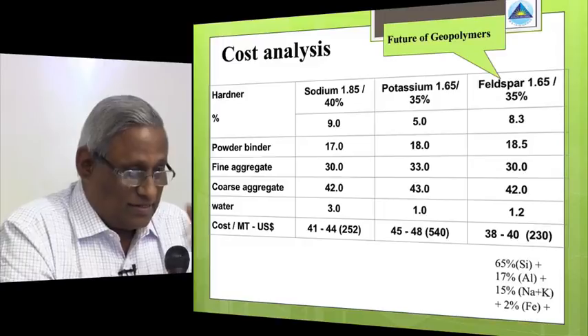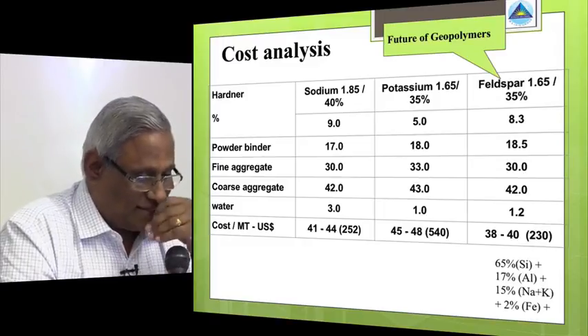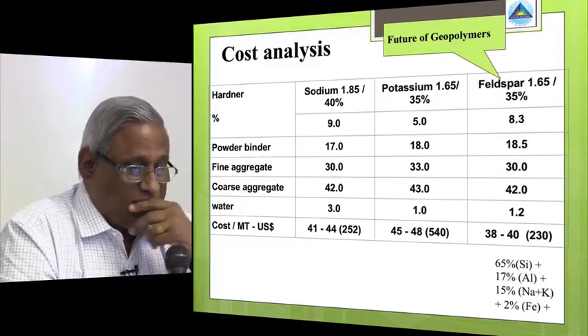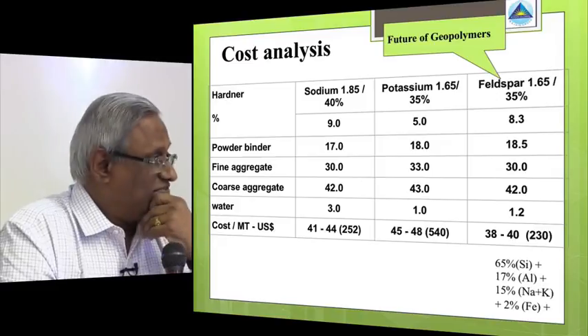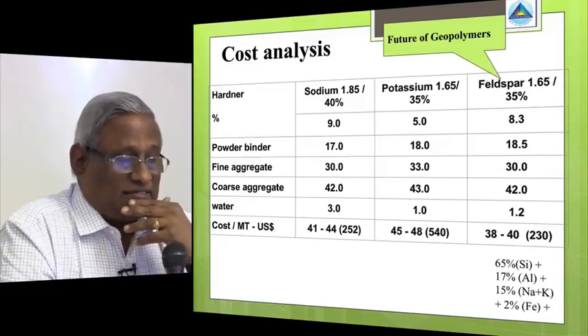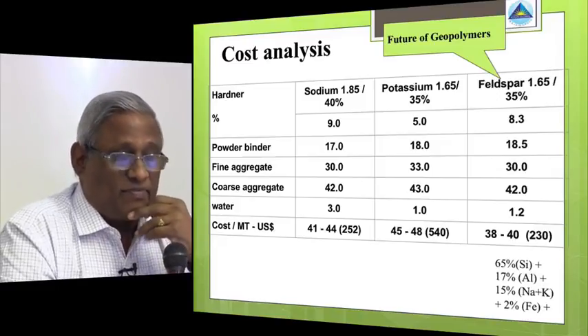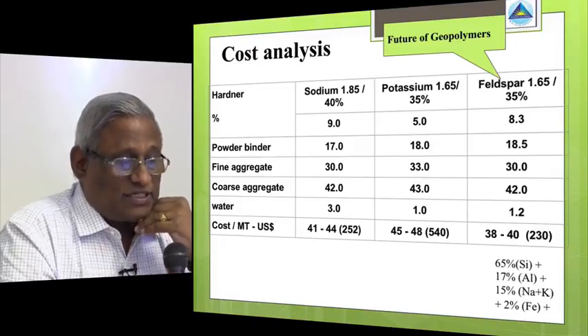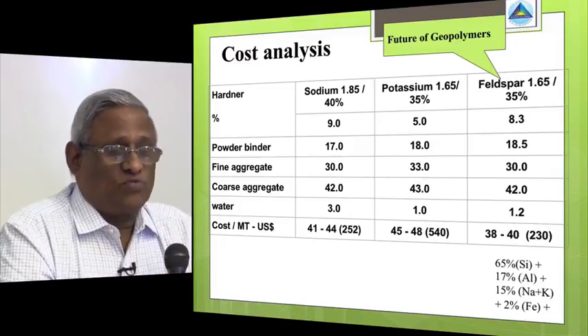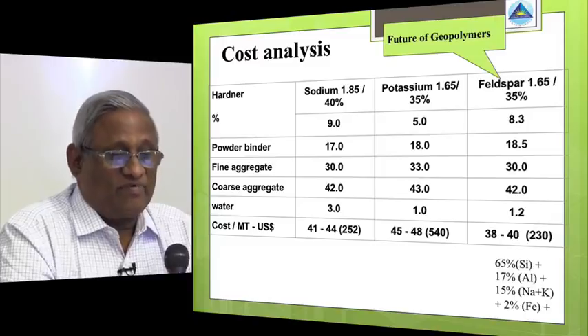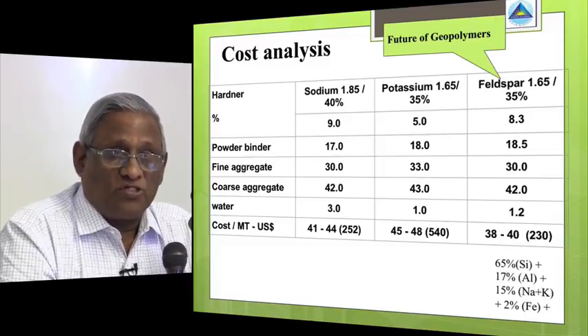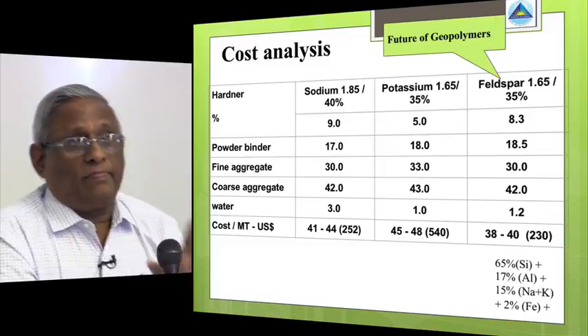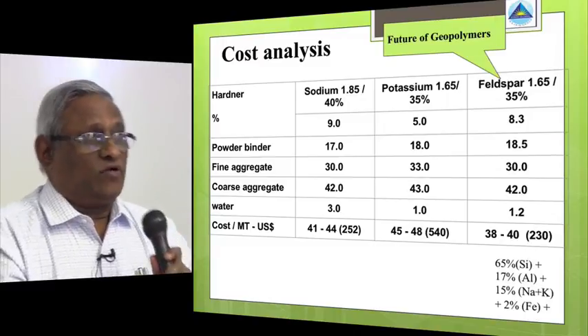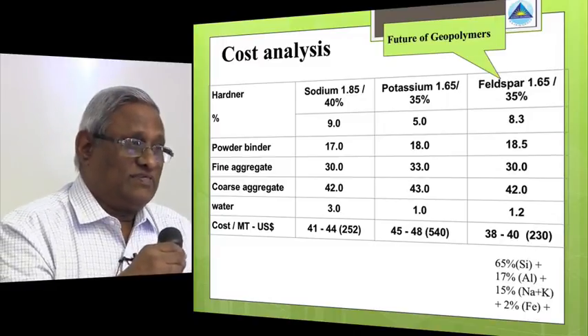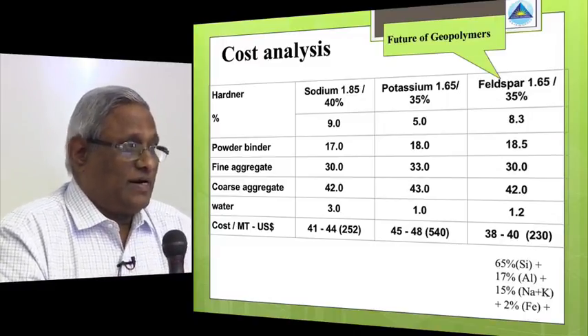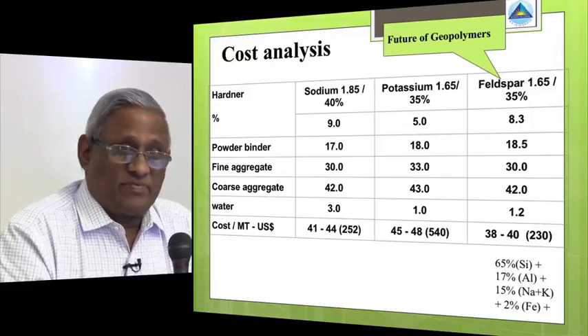I have made the feldspar a small combination there. The feldspar that we use has 65% silica, and 17% alumina, and 15% sodium and potassium, and 2% iron, and plus 1% of others. And this is the type of feldspar that we have been using to make an activator. This is a new one, and we are just filing the patent, and we already hold 3 patents of different products.